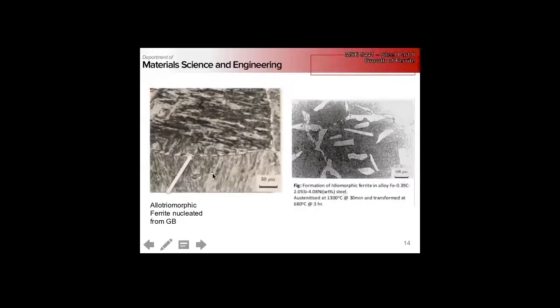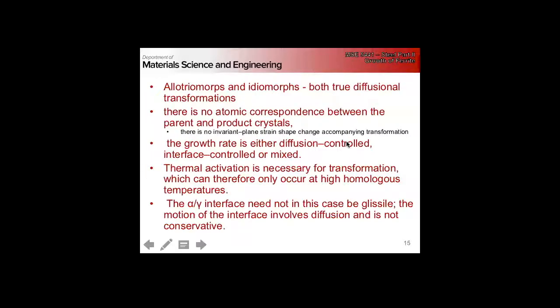So here we can see allotriomorphs that have nucleated and started to grow, and they haven't connected to form a complete film here. And here's just a micrograph of ferrite idiomorphs hanging out in the interior of the austenite grain.